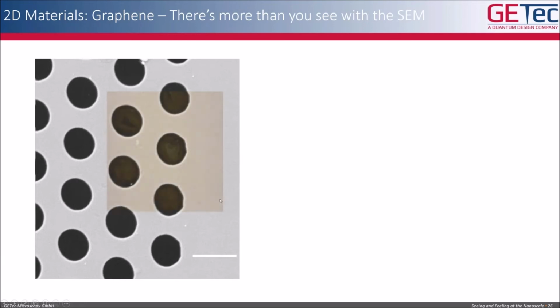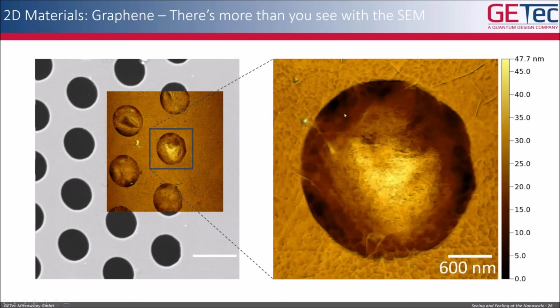But if you now come with the AFM and take a correlative image, you can beautifully resolve how the graphene is really covering these silicon nitride holes. You see some attachment at the edges due to van der Waals forces of the graphene, and in the middle, the graphene is even bended a little bit upwards.